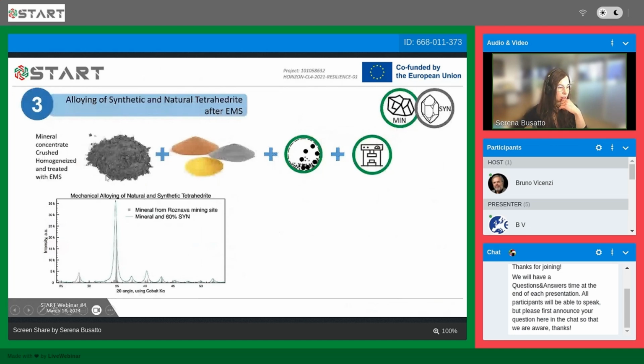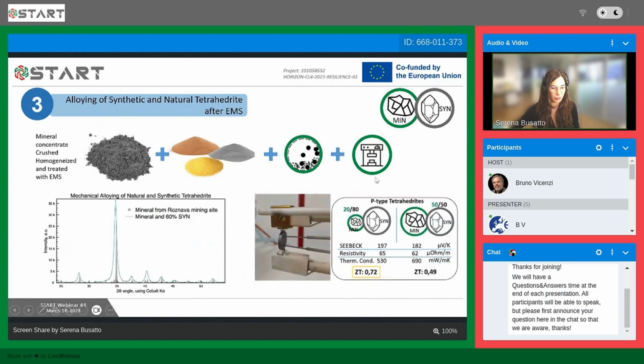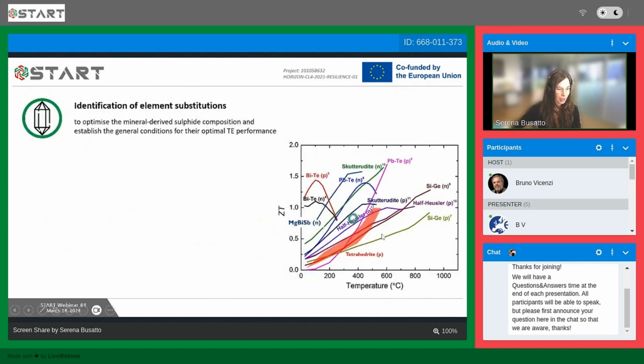And in the end, what we did was to mill together, as I showed you before, part of mineral concentrate crushed, homogenized, and treated by electromagnetic separation, balancing the composition with synthetic powders. Then we ball milled, sintered the material, and measured the thermoelectric properties, and we found that the ZT values of these samples containing mineral and synthetic elements are good also compared to purely synthetic tetrahedrite examples reported in the literature. Okay, they are here. You can see them in this region of the graph. So for now, it's not a bad result.